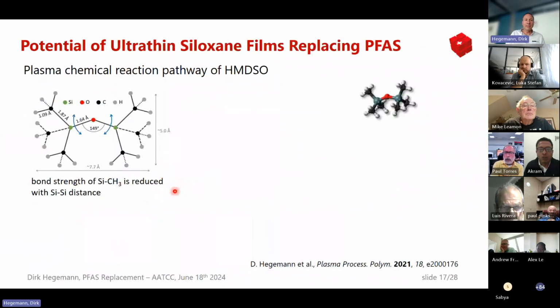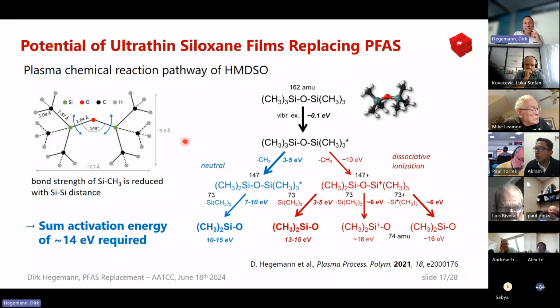Look into more detail, taking this hexamethyl disiloxane as a model molecule that can enter the plasma. Typically, as soon as it enters the plasma, it gets already vibrationally excited. So very low energies are sufficient to break bonds, to do chemistry, as mentioned, in dry conditions close to room temperature. And then you might have different branches of reaction pathway, and you can look at what might be the energy to get those film-forming species.